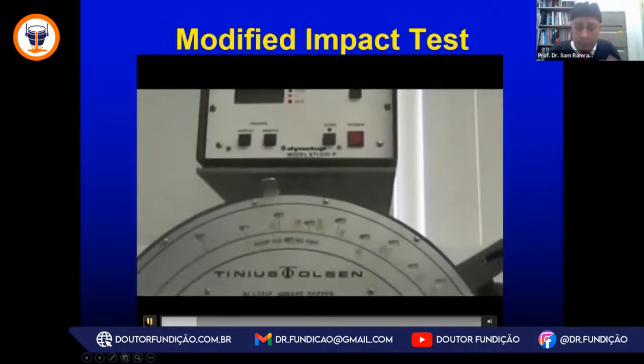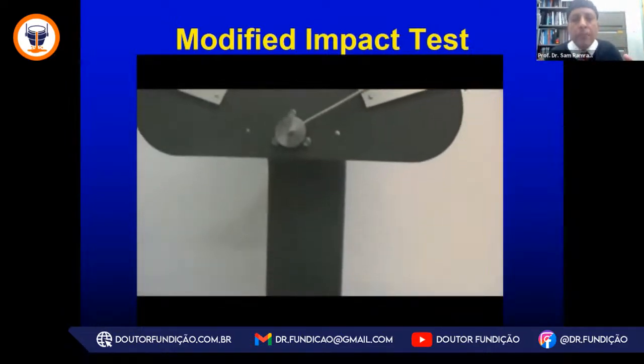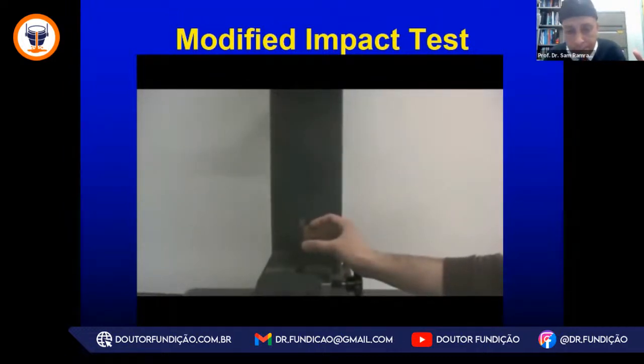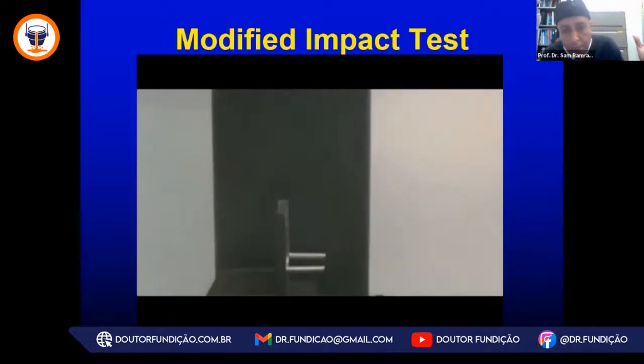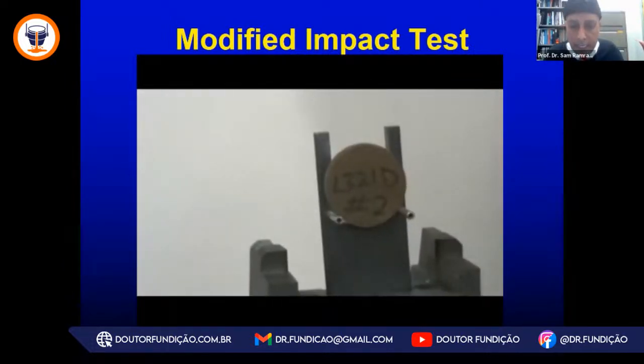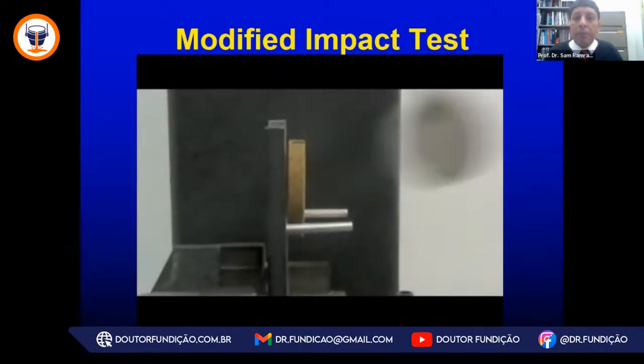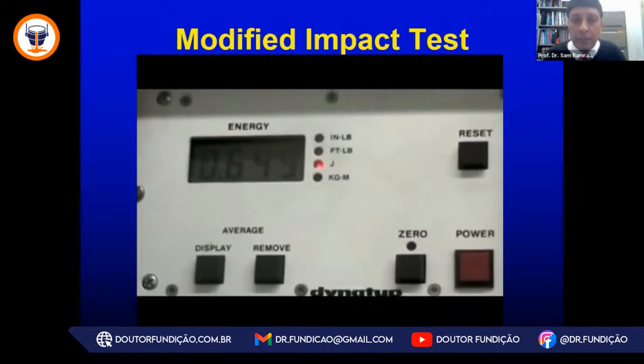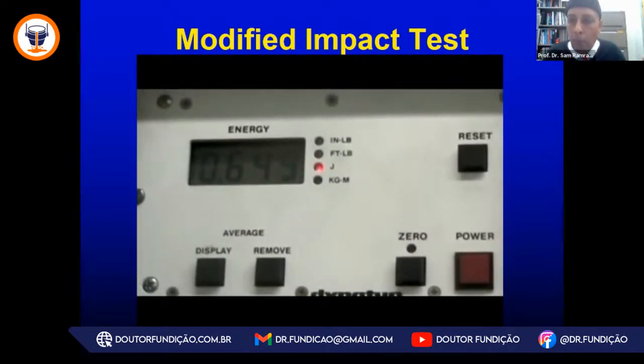And how this test works is that we support a coupon on a goalpost. It's a simple setup, like a rugby goalpost, and then we impact that specimen symmetrically. That particular idea gives us, again, the energy of how a core or mold could fail in shakeout. So if we have the energetics, the energy in joules, as we make this chemical binder system, and we understand that chemical binder system after heat exposure, and we can measure its toughness, then we can use the same energetics to develop our shakeout equipment for a sand binder system.